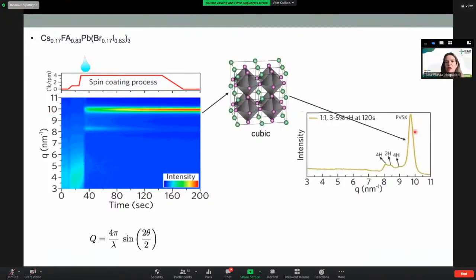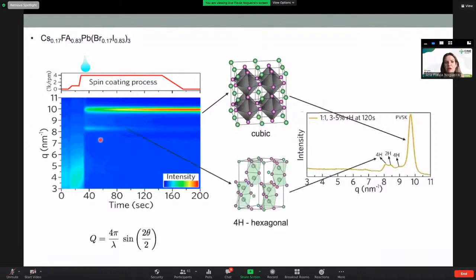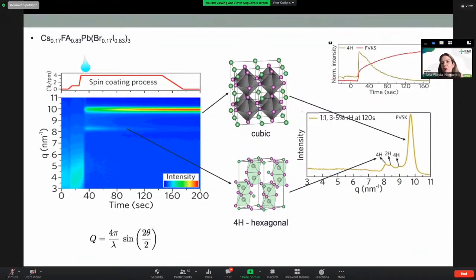So here in this case, I just integrated this spectrum here. But we also see the formation of other signals that correspond to what we call the hexagonal phases. And one thing that's interesting when you have this data from the synchrotron is that you can plot intensity with time. We observe an increase in the intensity of the signal from the cubic perovskite and a decrease in the intensity of the signal for the hexagonal phase. It means that before the cubic phase, we are forming the hexagonal phases, and these hexagonal phases are being converted to perovskite along the process.